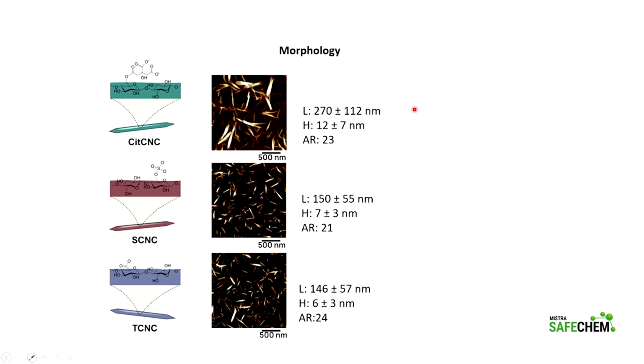If we look into detail to the morphology, we can see these rod-like structures that I previously showed. And we can see that they have different changes in the morphology depending on the route that we use. So then we can tailor the properties of these materials. If we look a little bit at the surface charge, this is a very important parameter when it comes to the application of these materials. We can find that they are in the same order as virgin sources.